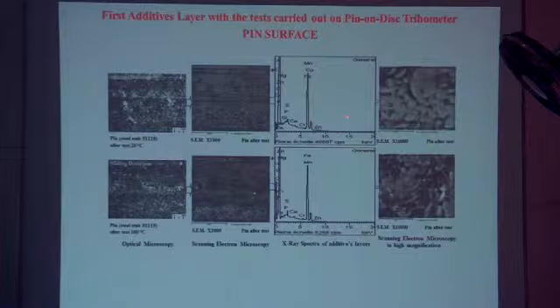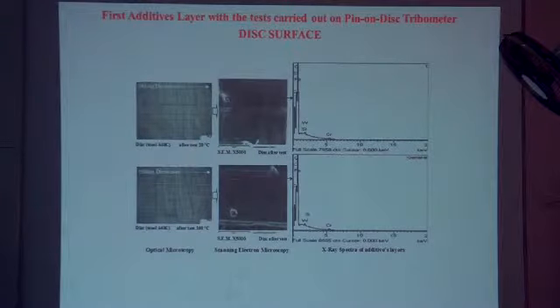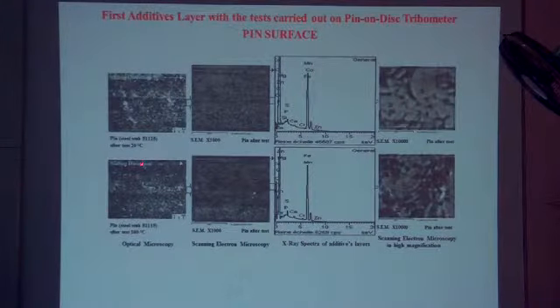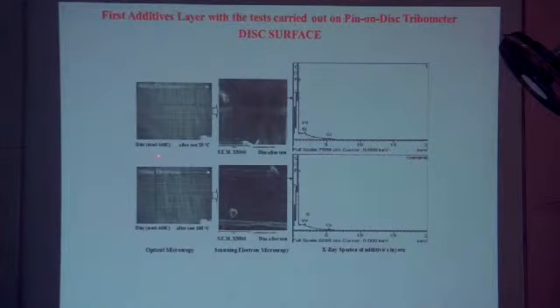When you look closely, calcium, sulfur, and phosphorus exist on the surface that formed this layer. On this surface, as I told you, it's a different material because this is 51,115, and the disk is 42C, where the material has much more chromium. I have another slide where I know the composition, if you're interested.